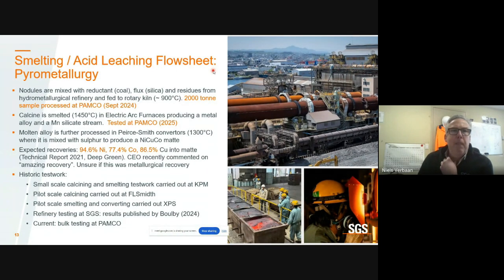The nodules are mixed with a reductant, the flux, and the refinery residues, and fed into a rotary kiln. So this is the calcination step. And they recently just announced that a 2,000-ton sample has been processed at PAMCO. So this is in September. The calcine is then smelted in an electric arc furnace producing a metal alloy. This too has recently been tested at large scale. And then this alloy is further processed in converters. And this is where a nickel, cobalt, copper matte is produced.